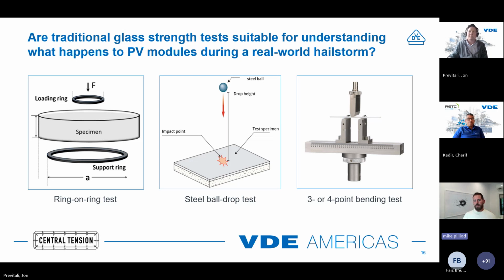And when you do a ball drop in the middle, that's looking at a direct impact, a blunt force direct impact. You can also do an impact with a sharp impact, like a diamond indenter, where you're looking at sharp impact on the surface. As you drop a ball onto the glass or shoot a hail ball at the glass, what happens with glass, and it breaks in tension, is as it hits the surface of the glass, the tension region is on the backside. So in that bending moment, you likely are failing on the backside of the top glass or the backside of the bottom glass in that format as far as a blunt impact. If you took a sharp impact and put it onto the surface of the glass, you would fail on surface 1 or the top surface.